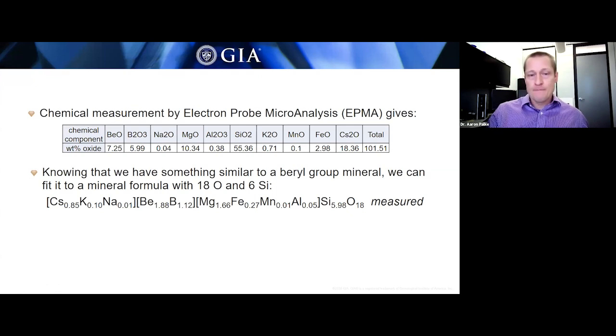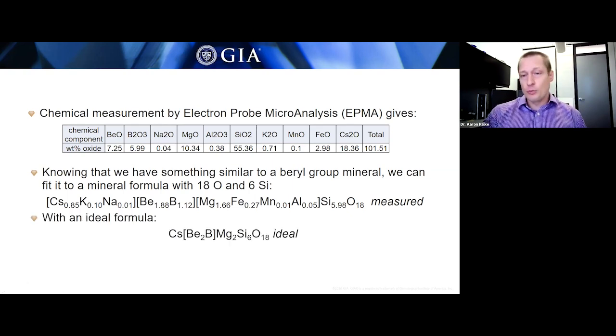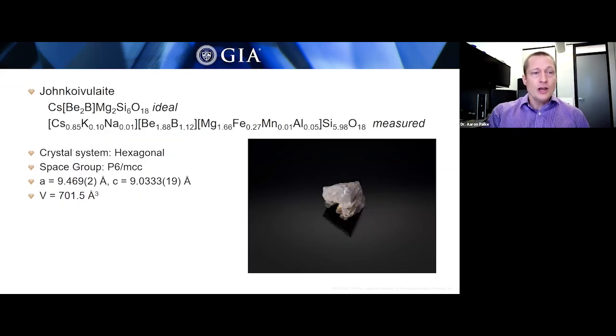But what we can do with this, these sites are dominated by a certain element. And so we can take this and simplify it a little bit. We can give an ideal formula to this new mineral. And that's here. So the ideal mineral formula is cesium, beryllium 2, boron, magnesium 2, silicon 6, O18. And so again, this is fitting that beryl formula very well, but it's got a very different chemical formula from the beryl. And we're going to get into a little bit of that more in a few slides when I talk about the kind of mineral groups and what that means. So all of a sudden we have both the structure and we have the chemistry.